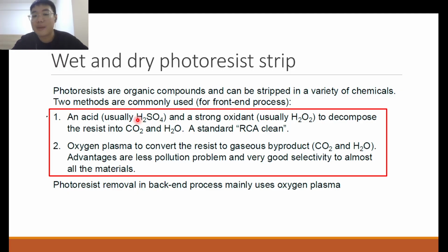So that's why in the back end process, we normally tend to use, if possible, this kind of dry etching, or dry photoresist strip through the use of oxygen plasma. And if your metal is exposed, we tend to avoid the wet steps, also because in a wet solvent, we may have other kinds of corrosion that may occur to the metal, like galvanic corrosion, etc. So that's also something that we want to avoid.